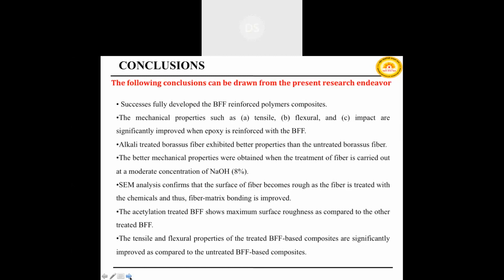chemical. The SEM analysis confirmed that the surface of a fiber becomes rough as the fiber is treated with the chemical, and thus the fiber matrix bonding is improved. The acetylation treated Borassus fruit fiber shows the maximum surface roughness as compared to other treated or untreated Borassus fruit fiber. The tensile and flexural properties of the treated Borassus fruit fiber based composite are significantly improved as compared to untreated Borassus fruit fiber based composites.